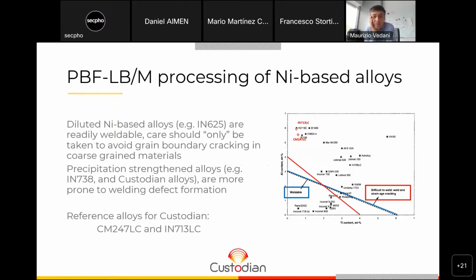Talking about the background on the metallurgy of nickel-based superalloys, and especially focusing on powder bed fusion processing by laser beam, considering processing of this material from the perspective of the material itself, we can draw some information also from the weldability. So the processing by powder bed fusion is strictly related to the weldability, since powder bed fusion is a kind of small-scale multi-pass welding, and the material feels more or less the same welding cycles. A material which is well weldable is also well processable by PBF and vice versa.